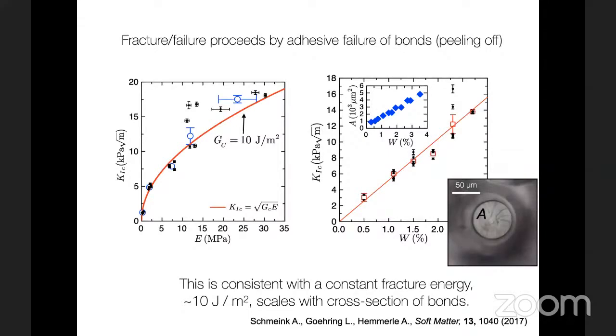Again, if we make more area of the bonds, we make them larger, the fracture toughness goes up and the amount of energy to peel them off goes up. That's the interpretation of the plots here, the measurements that we make, that there's a fixed fracture energy associated with breaking the bonds, which corresponds to a fracture toughness or Griffith condition for fracture propagation.